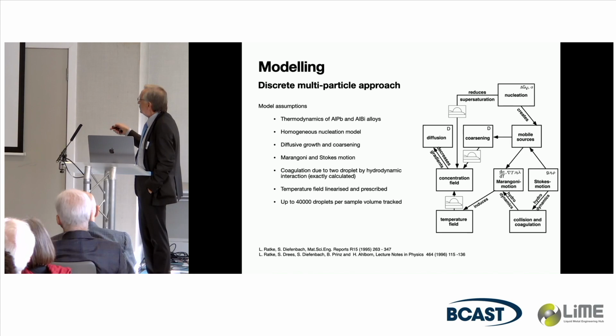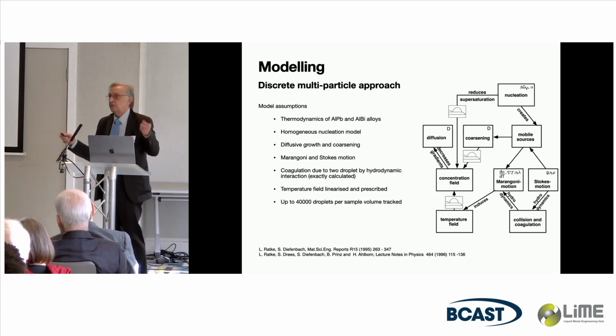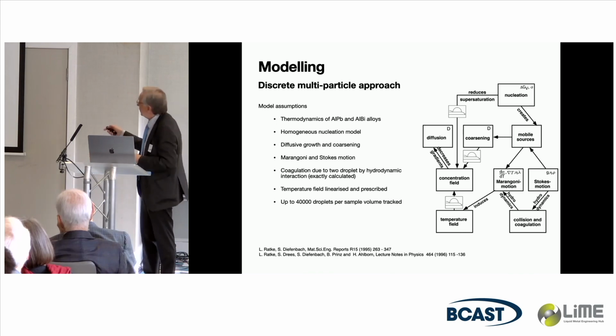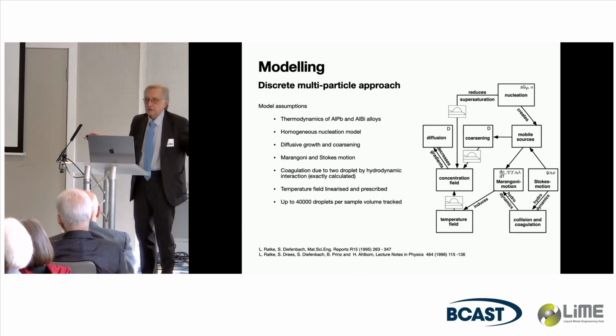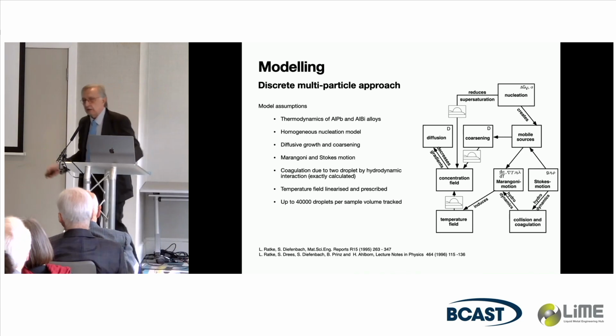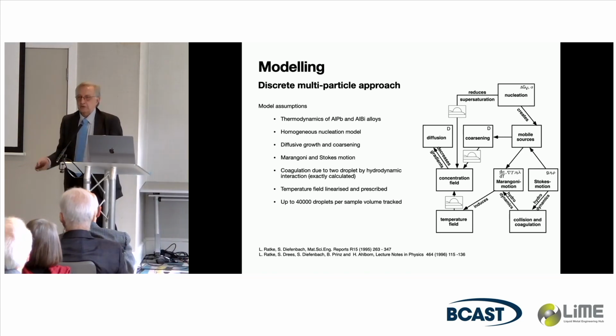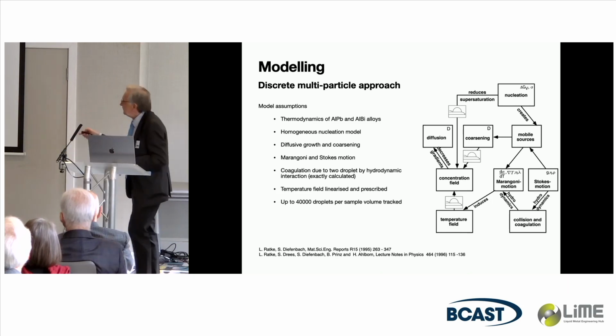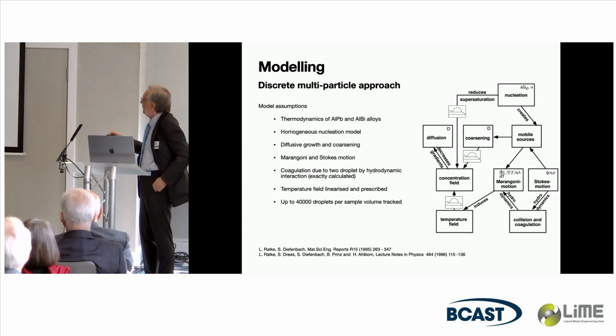Then if there's a nucleation event, you have to take into account that the drops move, so you have mobile sources of temperature and solute, not to forget that. The mobile sources, of course, do diffusional growth in parallel. You could do coarsening in principle. So if you do that numerically, you can also calculate Ostwald ripening, although I would say it's too slow. But nevertheless, you put that into the equations. This changes, of course, all the temperature, the concentration field, the Marangoni and Stokes motion.